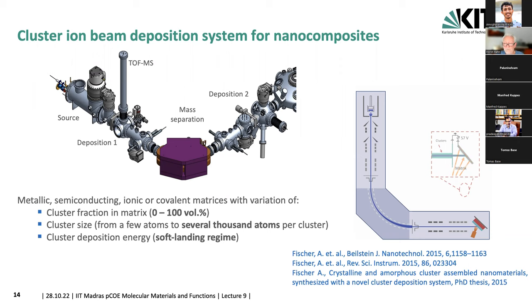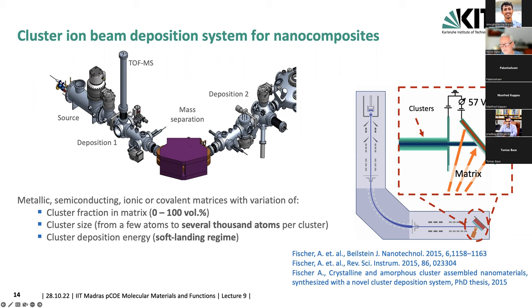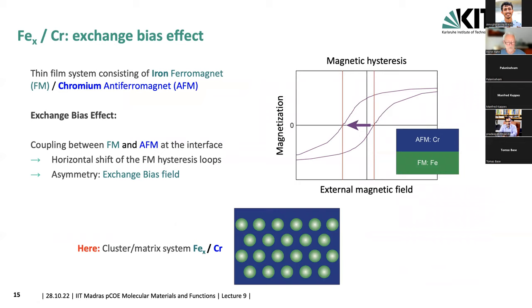So here you can see how the cluster beam in the second deposition unit over here is shaped, and we can deposit it over here, and then at the same time we have the matrix atoms coming and building this cluster matrix composite. So let me show you a first example, and this is iron clusters in chromium. Before that, we had done iron and silver, which is again a fully immiscible system, but there is no magnetic interaction between iron and silver. It was just a proof of principle whether we can prepare something like that. With this experiment, we wanted to do a little bit more magnetic characterization.